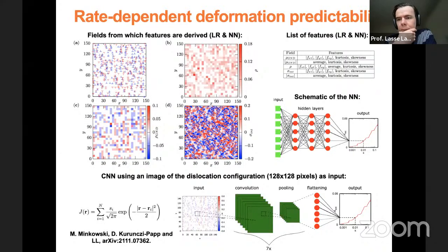So just to go through again this feature extraction process. You have this initial configuration that might look like this, and you can extract different fields from it. So here is, for instance, the dislocation density field. Here is the density of the geometrically necessary dislocations. So it's just the difference of the density of the positive and negative dislocations, which are the blue and red ones here. And then you can also look at the internal stress field.